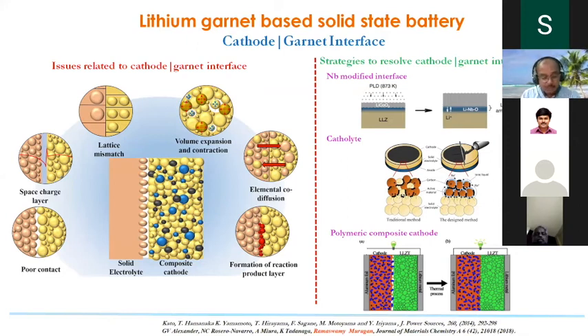So as far as I am concerned, people have improved dramatically the production of lithium garnets. Already ceramic processing technology is matured. So we have several techniques, starting from the film casting technique to the roller casting and tape casting techniques. People are able to make 50 micron thickness garnet tapes, a few meters or 50-meter tape rolls, also visibly I could see from the industry. Very good, reasonable conductivity of 7 into 10 power minus 4 siemens.